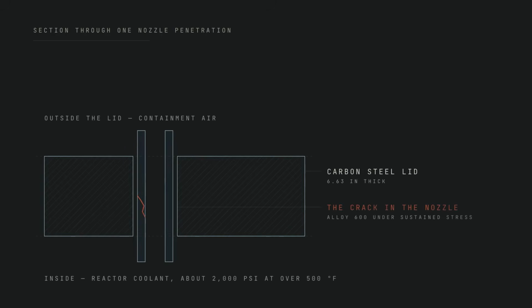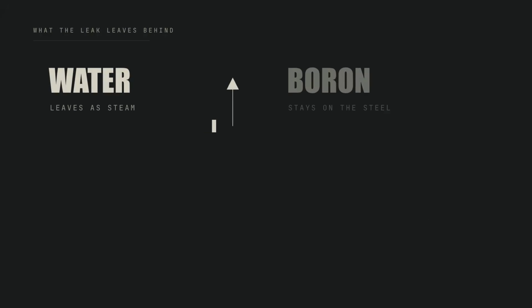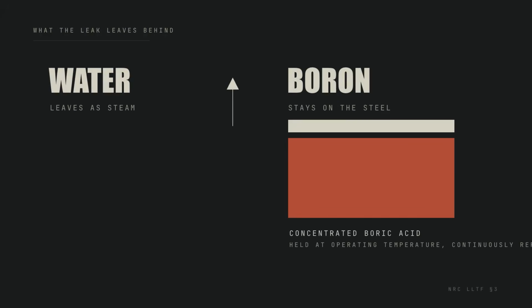Here is what that weep does when it reaches the outside of the lid. The coolant is water with boric acid dissolved in it. On the far side of the crack, the pressure drops and the water flashes to steam. The water leaves. The boron does not. What is left behind on the steel is concentrated boric acid, held at operating temperature, continuously replenished by the leak. That is not a chemical spill. That is a chemical reactor you have accidentally built on top of your reactor.